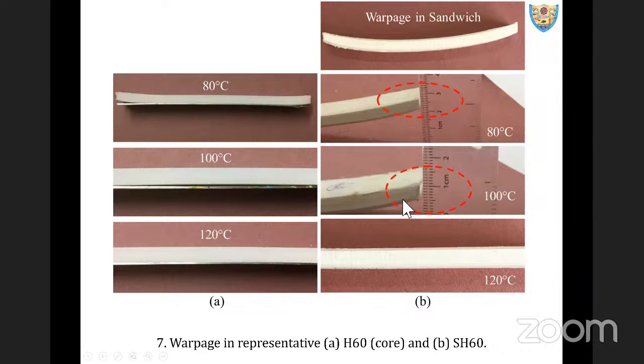But what we did observe is warpage happening completely post printing. So for that, we need to look at the suitable chamber temperature. Many printers are open architectures wherein it is not possible, but wherein you have an enclosed chamber, you can play around with the chamber temperature so that you can maintain a proper gradient during cooling or the annealing process, as we call it,